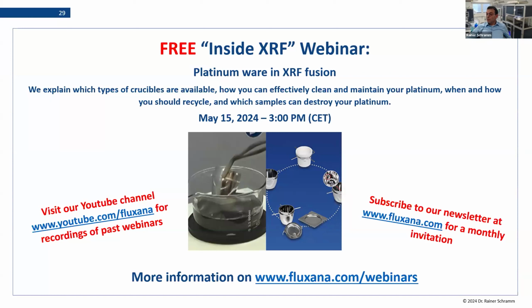So another question here. Wow, there are many questions. What oxidation agents can I use for a non-oxidized or semi-oxidized sample, and how are they added? I would say a very general oxidizer is strontium nitrate. You mix the strontium nitrate with your sample, and this mixture is placed on top of your flux. Then you go at a lower temperature, let me say something between 600 and 800 degrees, into the furnace. It could be a standard muffle furnace, and you let it oxidize 10, 15, 20 minutes. Then you take it out. And then you go to a normal fusion system. This is the principle of how you can do it.